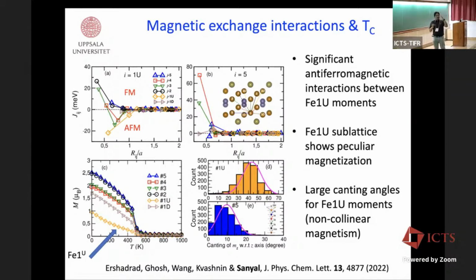Basically, we looked into the spins and measured the canting angles from the easy axis of magnetization, which is out of plane. This is the histogram that you see for the iron 1 magnetic moments residing in the iron 1 up sublattice. If you measure the canting angle from the positive Z axis, which is the easy axis of magnetization, you see there is a peak around 40 degrees of canting. If you go to another sublattice, the iron 5 sublattice, which shows a more or less usual M versus T behavior, you see that the canting angle is rather small, around 10 to 12 degrees.